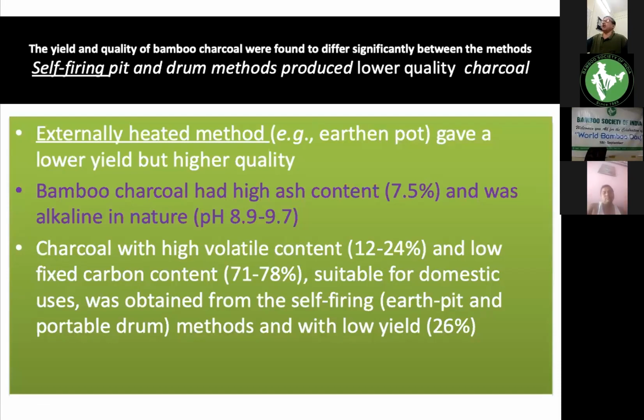And with high volatile content, about 12 to 24%, and low fixed carbon content, about 71 to 78%, suitable for domestic uses, it was obtained from the self-firing method, that is the pit and portable drum method, with a low yield of around 26%. So this shows that the country method gives a volatile content a little bit higher.